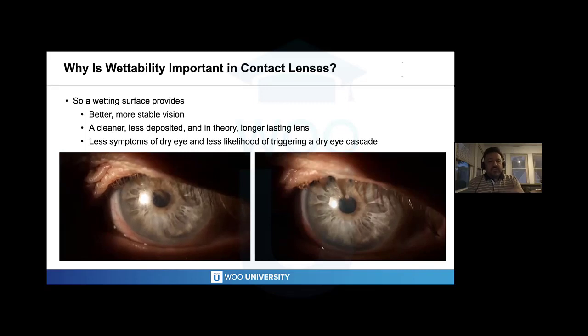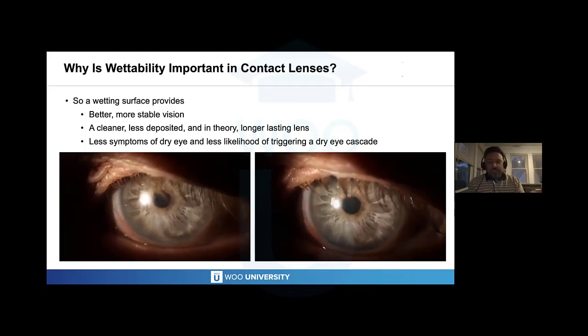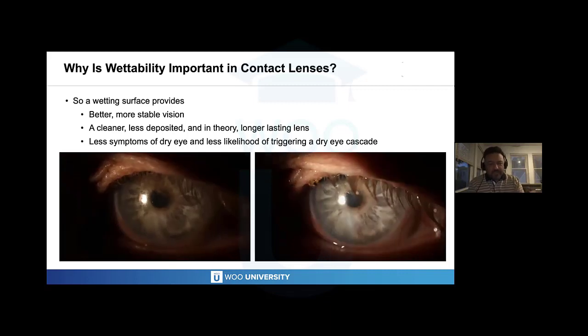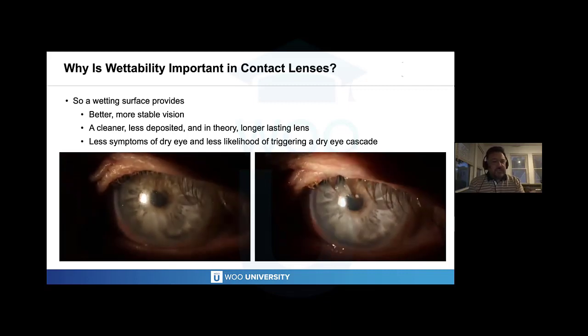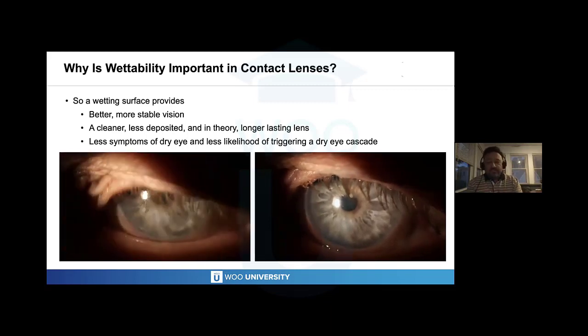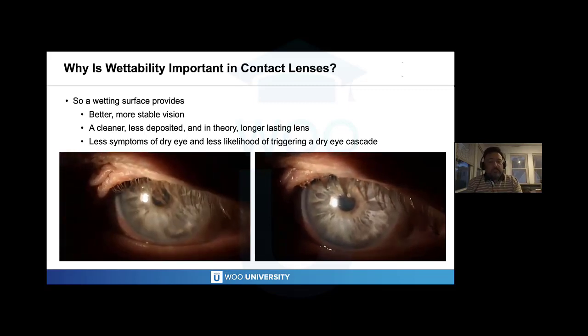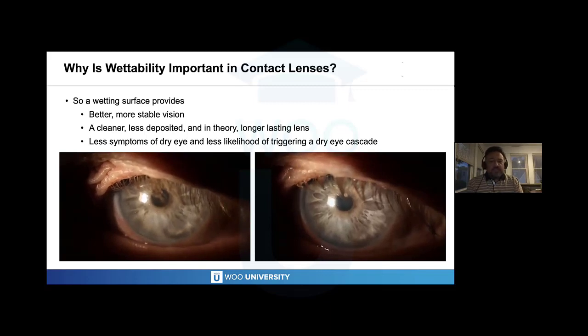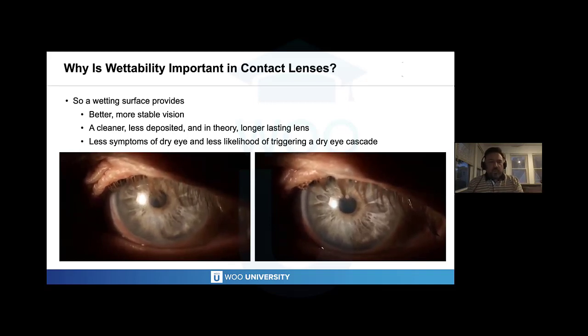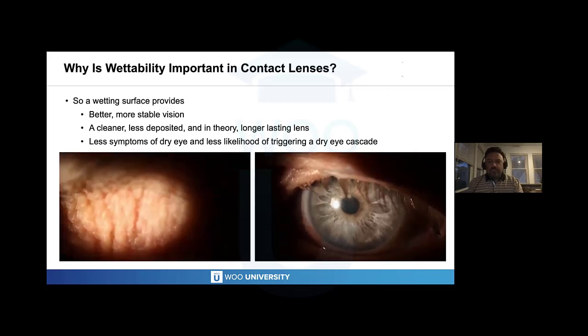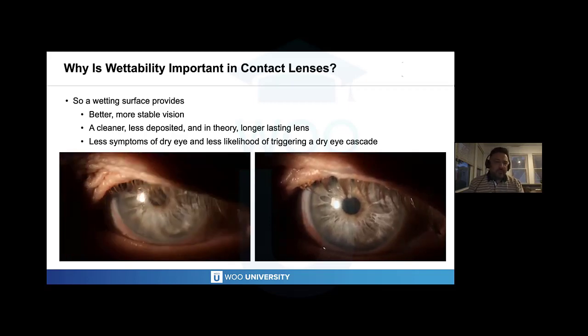You can also see that tear layer evaporating 4 or 5 seconds after the blink, as you can see by the reflex on the surface of the lens. The picture on the right is a lens that has a coating on the surface to help maintain the wettability. It's a significant difference in the patient's experience, both in terms of vision, comfort and deposits. So creating that more wettable surface is hugely important to our patients' wearing experience.